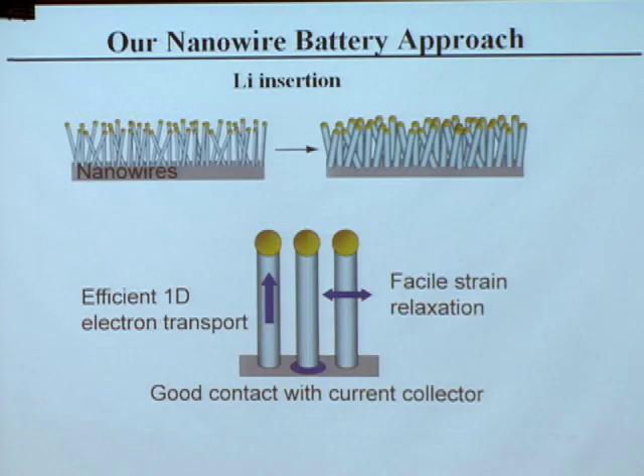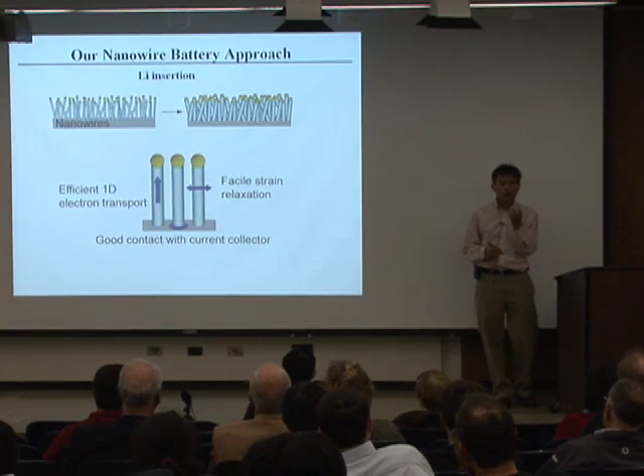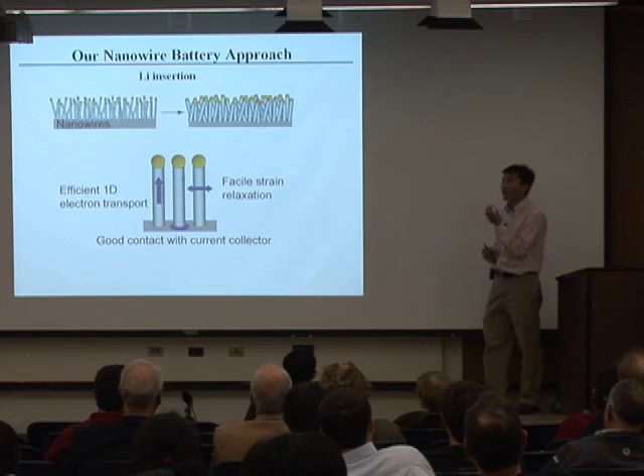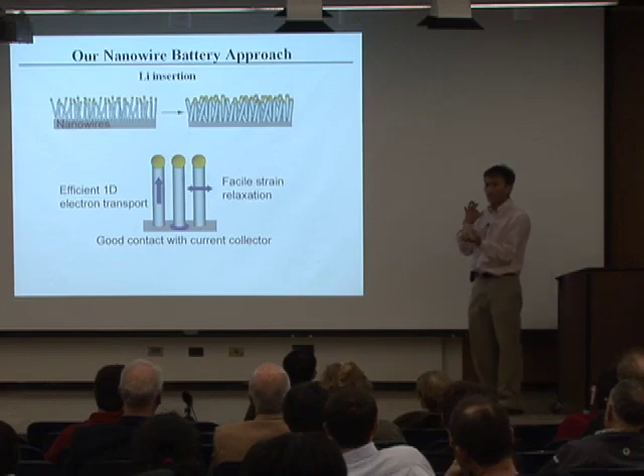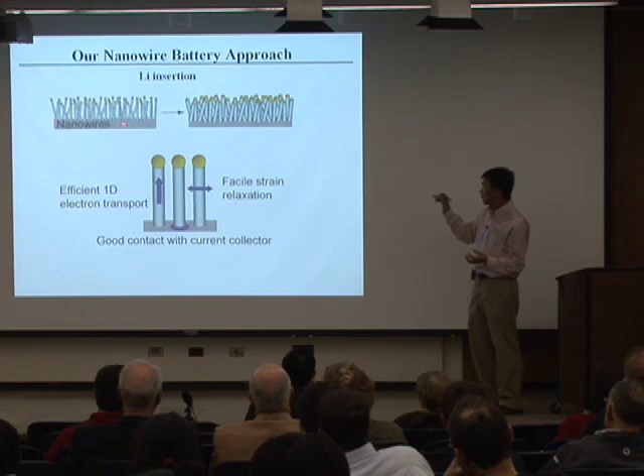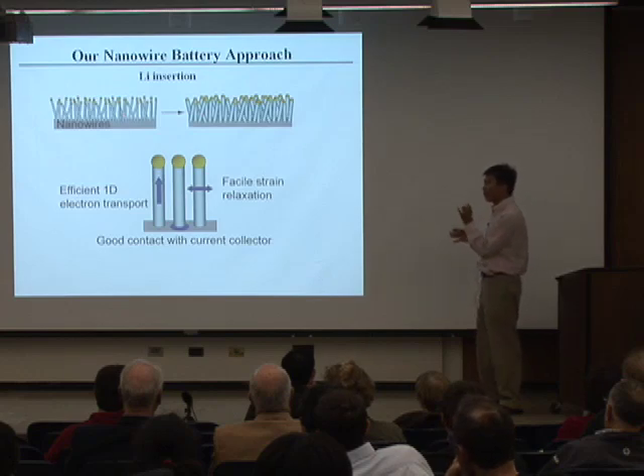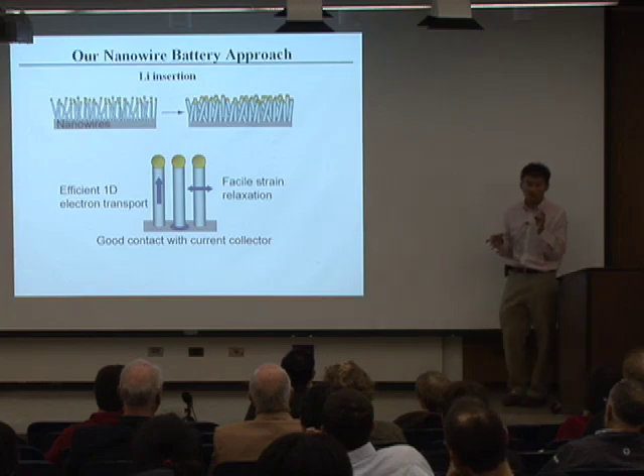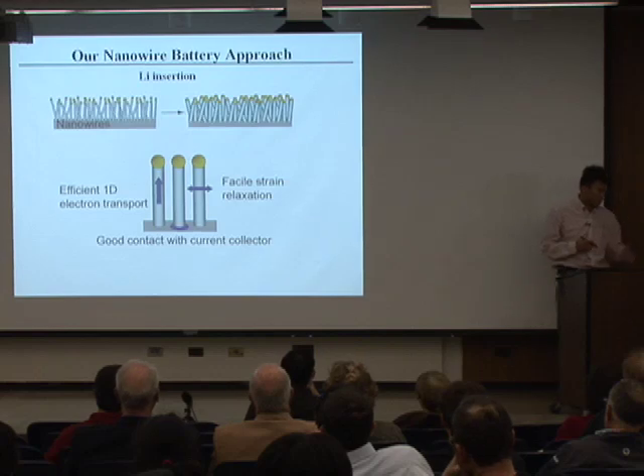I mentioned to you, nanomaterials in general have two advantages. One is the shorter lithium diffusion distance, so lithium can come into the center of the material very fast. And second is very efficient electron transport. For the materials which can store a lot of lithium, you gain one more advantage. That is, when you have large structure change and volume expansion, they don't break. For example, you take a nanowire growing up from a metallic substrate surface, lithium ion comes in, they expand, but they don't break because each of these nanowires is small enough to take the strain induced by the structure change.